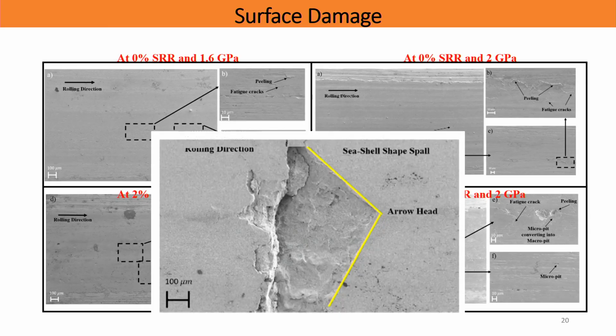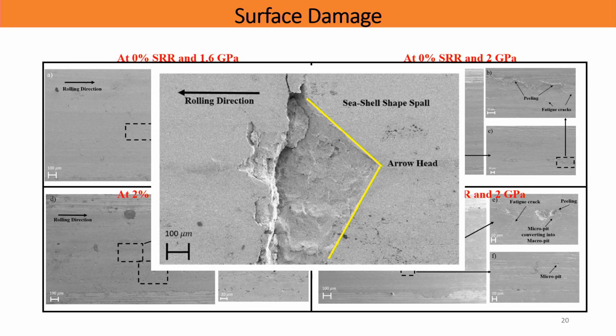So if you see the surface, the cracks in the rolling direction, there are seashell shaped spalls which are created, and these join up and make pits and micro pits. One important thing which I got from the previous lectures was that there can be cracks generated from the surface, and there can be cracks generated from the subsurface, right? So cracks generated from the surface are basically formed because of the surface roughness. And of course, we have had a long discussion on this.